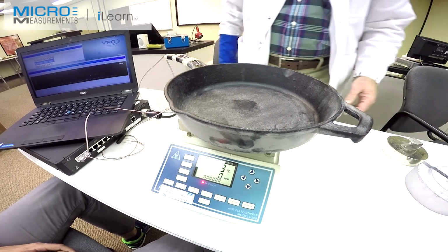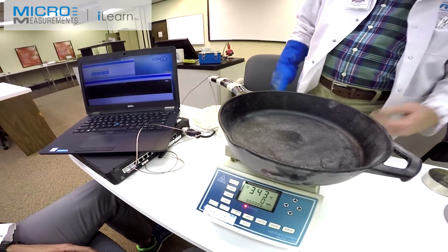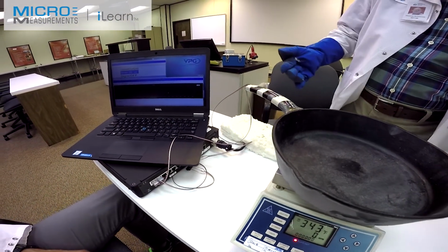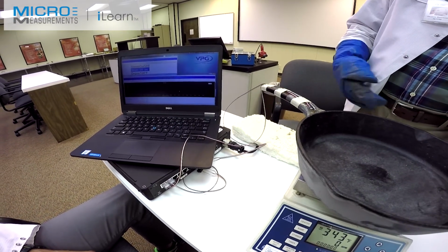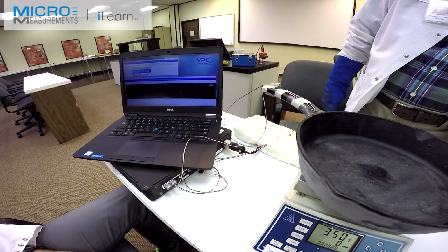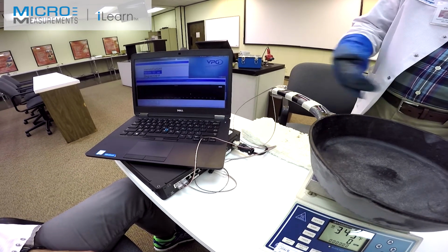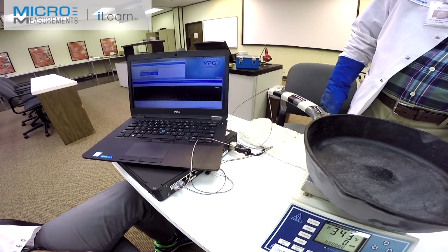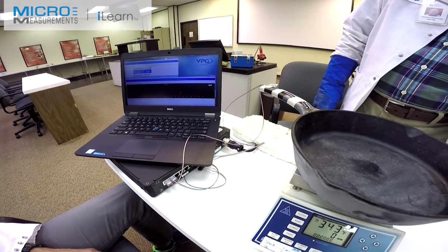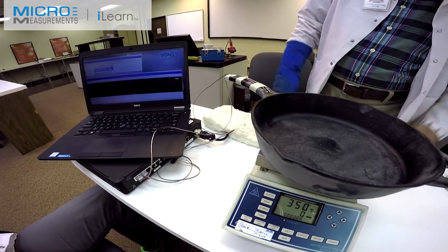So it appears, based on our numbers, that we didn't have a very large change in strain based on the fact that it's gotten warmer. So it tells us this cast iron frying pan, even though you're getting up into the 150-200 degree range, is not going to change strain very much. You've still got a very safe pan.